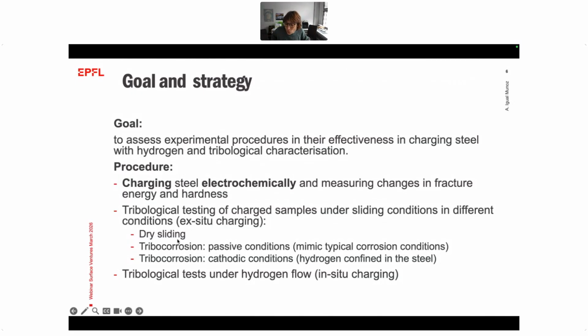To do that, we do dry sliding, but we also use the triboelectrochemical setup to impose certain surface conditions: passive conditions to mimic typical corrosion conditions, for example for steel, and cathodic conditions to keep the hydrogen inside the material and avoid that it escapes during the tribological testing. And then the second part: one thing is this ex situ charging, but then we went one step further and tried to do the same with an in situ charging, which I will explain later, that was done in collaboration with ERTEC.